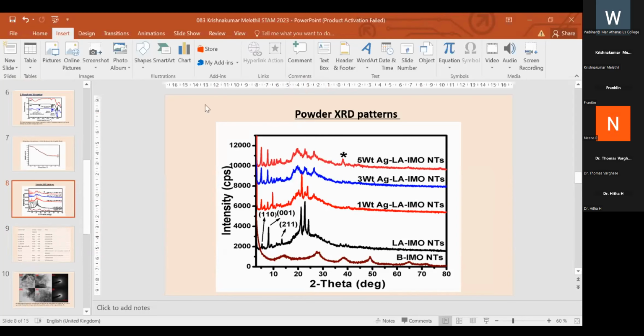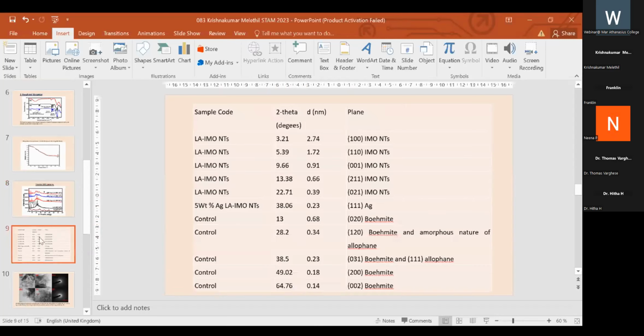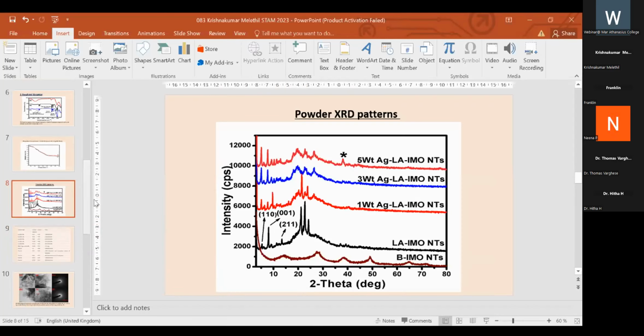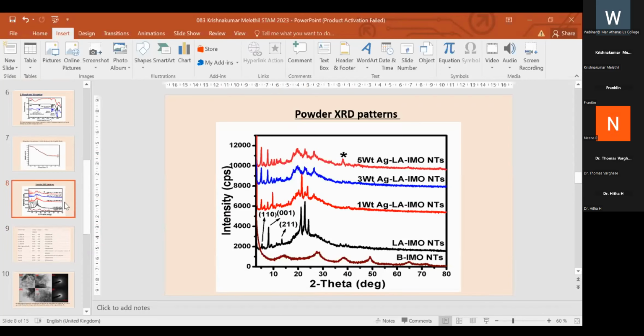But in the case of lauric acid loaded samples, we get many peaks of imogolite. This is the 110 plane of imogolite, and the 001 and 211 peaks of imogolite. We can also observe a peak at 3, which is the 100 plane of imogolite. When we draw with more resolution, we can observe that peak. This is a major peak of imogolite, passing through the center of the imogolite nanotubes.